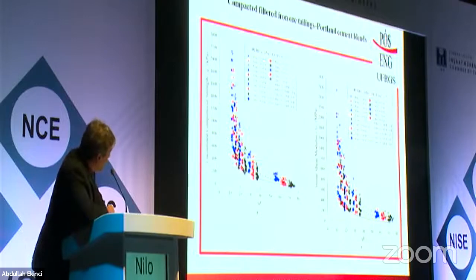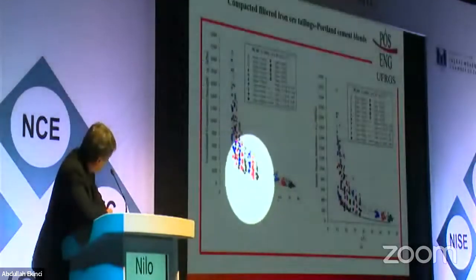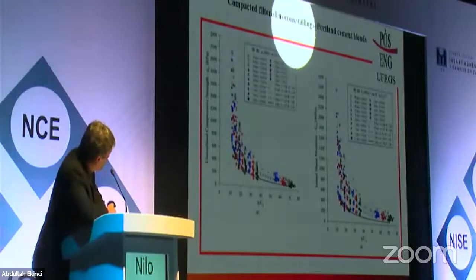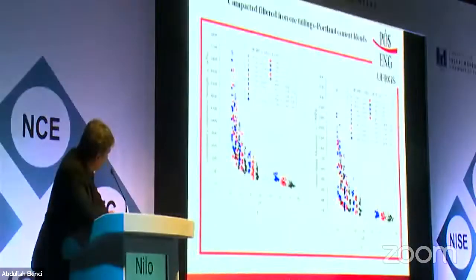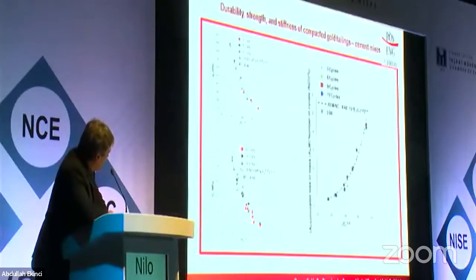So this is for results for several. Each one of the curves is for a different curing time, but the unconfined compressive strength for this iron ore tailings with Portland cement, and this is G0, which is the initial shear modulus that we have had. Here it's, I'm gonna go after.